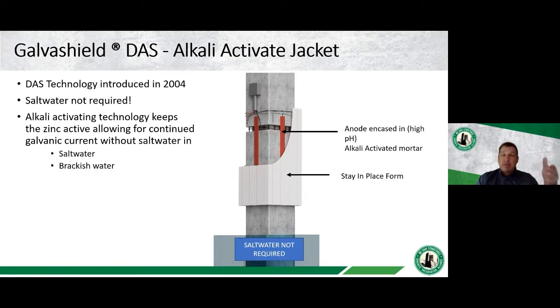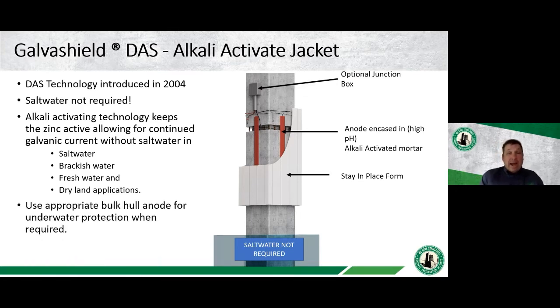One of the other things that can be done is once you get into brackish water, where maybe your chlorides or salt levels are not high enough to activate the zinc in a traditional zinc mesh or the Tidal Plus wicking anode, we can use these anodes as well in a brackish water environment, because we're not relying on that salt water. Another thing to note is it can also be used in a freshwater environment and dry land applications. So if you're even thinking of de-icing salts and some of the bridges and substructures up in the dry land areas, this can also be used there. Again, it can be used in brackish water, salt water, all these applications.